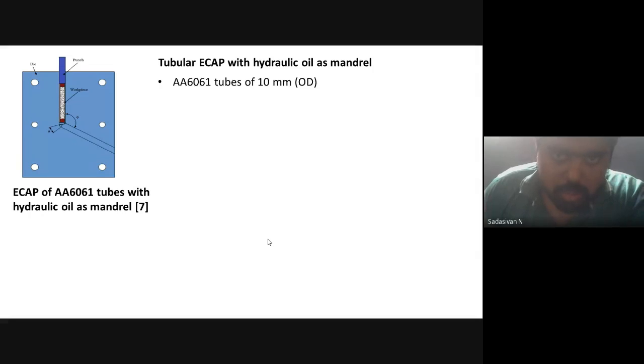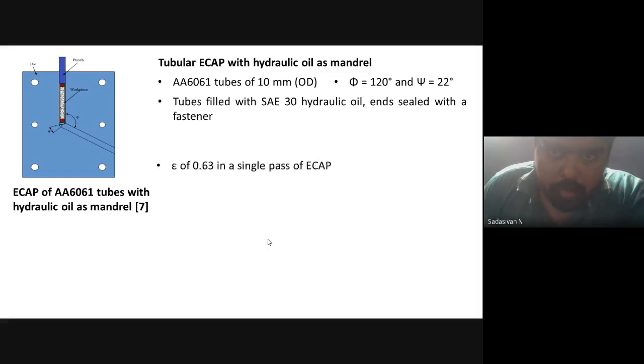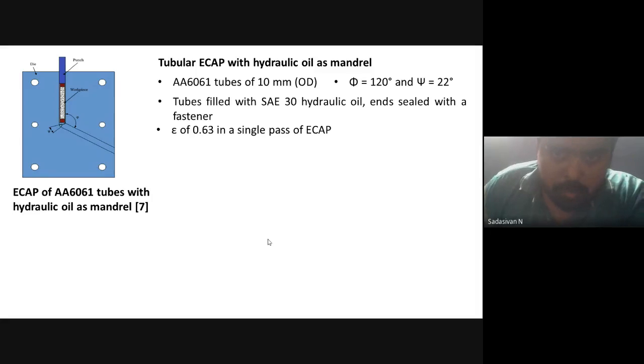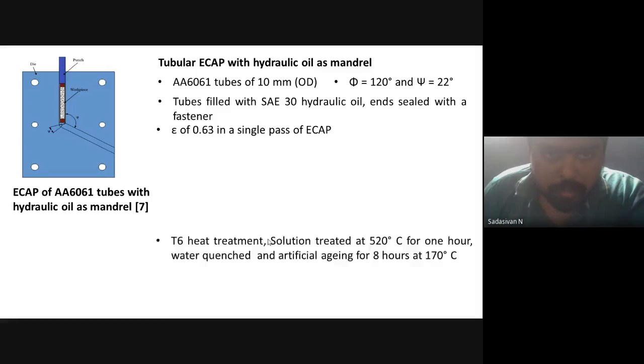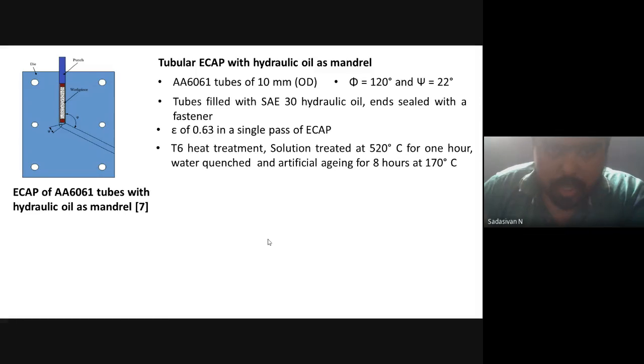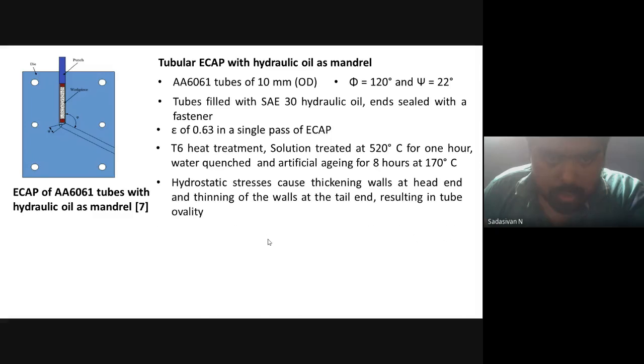Here 6061 tubes, 10 mm outer diameter, were processed in an ECAP die, 120 degree channel angle and 22 degree corner angle. Tubes were filled with SAE 30 grade hydraulic oil. Each step of ECAP imparted a 0.63 magnitude of plastic strain. After ECAP, I am performing a T6 heat treatment. The parameters are given here: 520 degrees Celsius solution treatment, after which I water quench, and then artificial aging for 8 hours at 170 degrees Celsius.